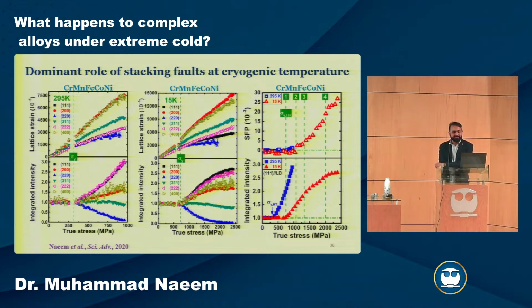You can see that the blue, which is at room temperature, 295 Kelvin, does not change, or very little. The 15 Kelvin one, you can see, is increasing with stress. Similarly with texture, which I represented over here for 111, the main direction where grains rotate towards for FCC materials. For room temperature it is increasing linearly, while for low temperature it has a very different kind of trend. From this we can tell the deformation pathway of the material, and relate it to how initially it was mainly dislocation, then there was stacking fault, then something else happening at the end as well. So basically we try to answer questions about the deformation pathway and understand what is happening with the material at low temperature.